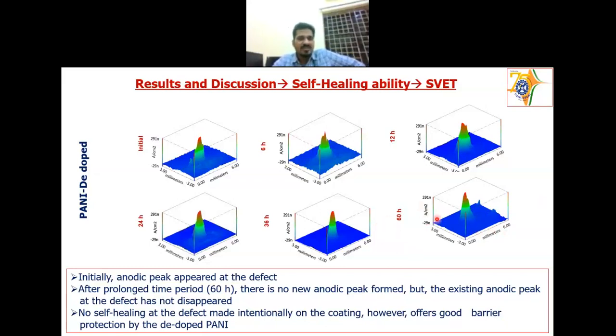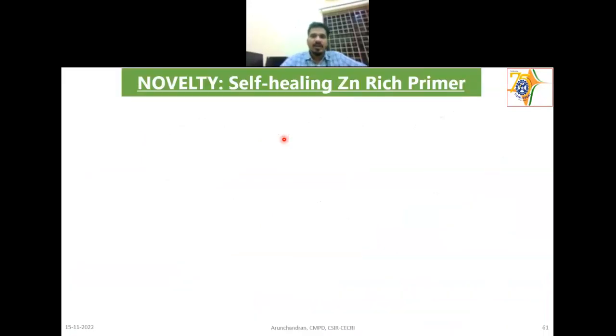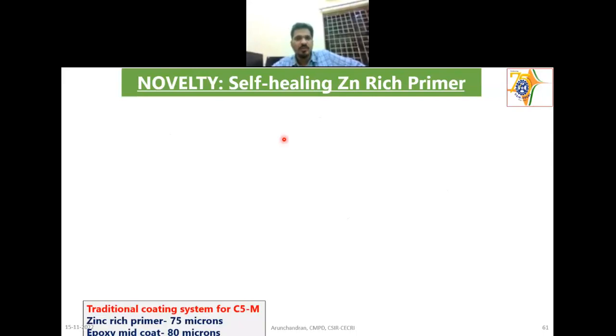We tried up to 60 hours, but there is no diminishing of the peak. At the same time, we can say that when you add dedoped Pani, the current value we are getting is in nanoamperes only, not microamperes as in the blank. So we can say it is able to give better protection as well as self-healing ability. And then there is another one, as I told, this Pani can be added into a zinc-rich coating also.